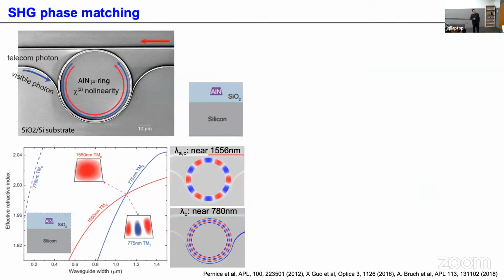So to have efficient light conversion on a chip, you need to satisfy phase matching. This is quite convenient with aluminum nitride waveguides, where you can do geometrical phase matching. You can vary the width of the waveguide, and as you vary the width, the refractive index of your fundamental mode and the harmonic mode can meet at a point, at a width like 1.1 micron here, and now you get phase matching. So you can support different modes that have the same phase velocity, and then you get phase matching.